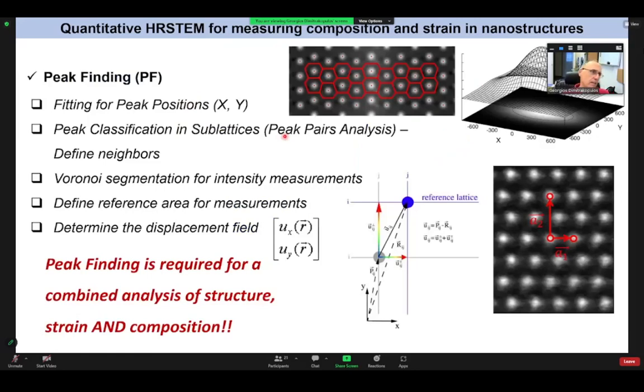Of course, you can do exactly the same thing with peak finding. Peak finding is not working in Fourier space, in the inverse space, reciprocal space. It's working in direct space. But it's doing exactly the same thing. It's measuring the positions of the atomic columns, and you can measure it with respect to some reference area. So you can again deduce the strain field in exactly the same way, but the additional advantage of peak finding for high resolution STEM is that you can also deduce the intensity of the atomic columns, and if you know what you're doing, you can deduce the composition. So you can correlate and you can check if your strain determination agrees with your compositional determination. Of course, this is not a very easy job. It's not straightforward to do it.